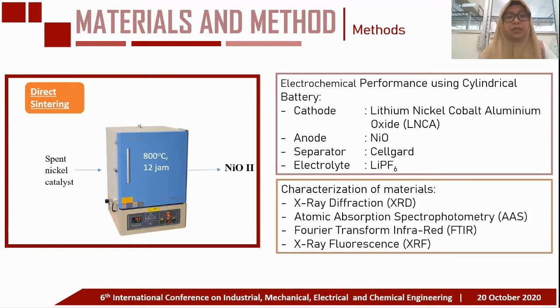Electrochemical performance was carried out using cylindrical batteries. The cathode, separator, and electrolyte used were LNCA, Celgard, and lithium hexafluorophosphate, and NiO as anode was mixed with NMP to form slurry, then coated on Cu foil. Then the anode sheet was dried in a vacuum oven at 80 degrees Celsius overnight until it was ready to assemble. The performance test was analyzed using a Neware battery analyzer and PDF software.